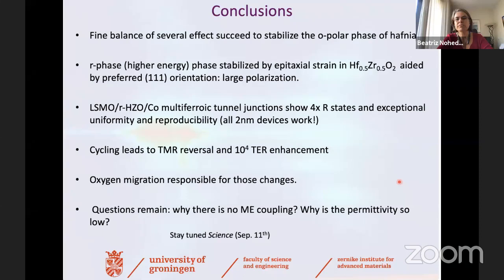So we have not yet had the chance to investigate very much what will happen if the material grows atomically flat, or with different growth modes, because there's not so much freedom you have in terms of getting a polar material. You need very particular conditions to get the material to be polar after growth.